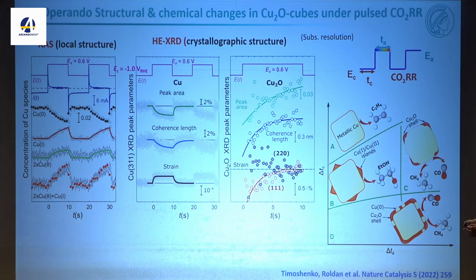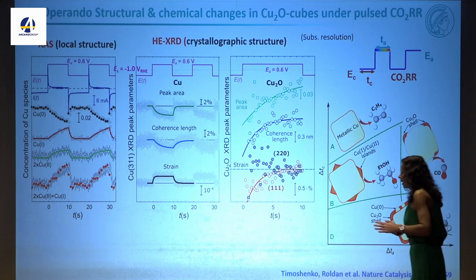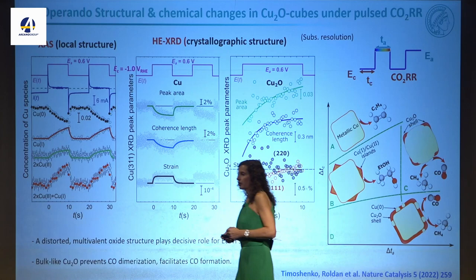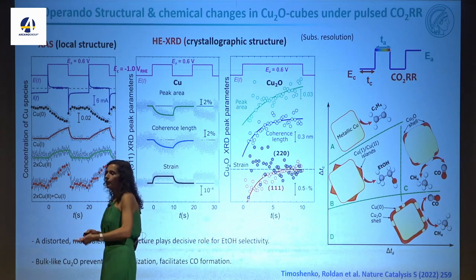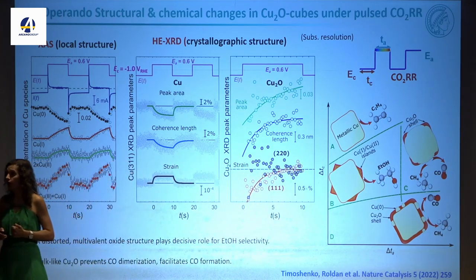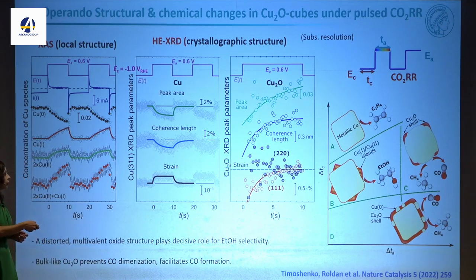If you start growing a very thick oxide layer, for example, long anodic pulses, you start making only C1 products, CO and methane. So now I can say, okay, I can design my material. I want these steps. I want the combination if I can leave some of this oxygen there. I know what to do with my material with this highly disordered copper 1 and copper 2 species.